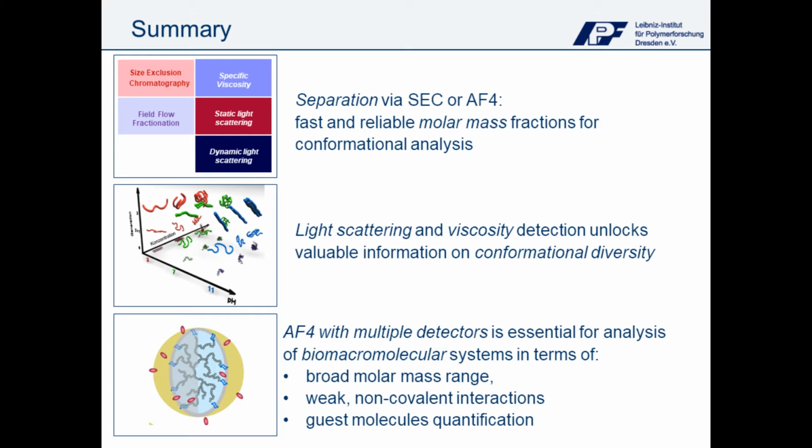Well, the experimental parameters are actually easy to optimize. That's not really the problem in such kinds of systems. I think that if we are considering quantification of the small drug molecules, or in this case the Rose Bengal molecules, during the elution phase, it will indeed not be easy because of a low concentration of these molecules, which can be collected after penetrating the membrane. Therefore, we are using here the focusing step, where at once, very fast, the small Rose Bengal molecules can penetrate through the membrane and can be very well detected.